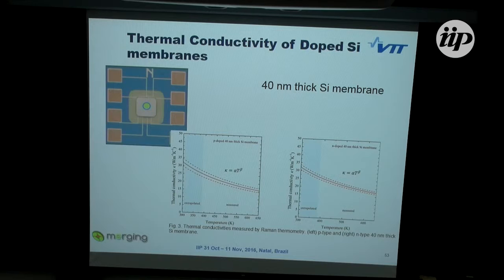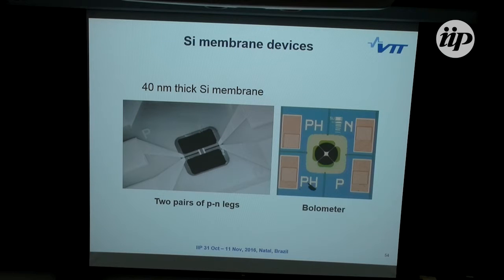The doping affects the thermal conductivity a little bit, but not too much. Phosphorus is about the same mass as silicon, so it doesn't affect too much. This was measured using the two-laser Raman thermometry, and the thermal conductivity in both cases is around 30 watts per meter Kelvin. So here are examples of the devices. This is a test device where we have two pairs of P and N legs.